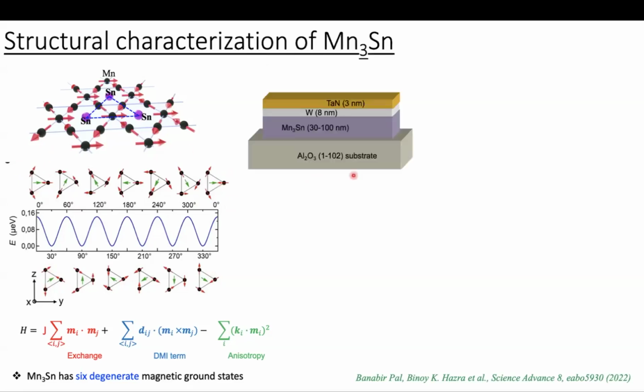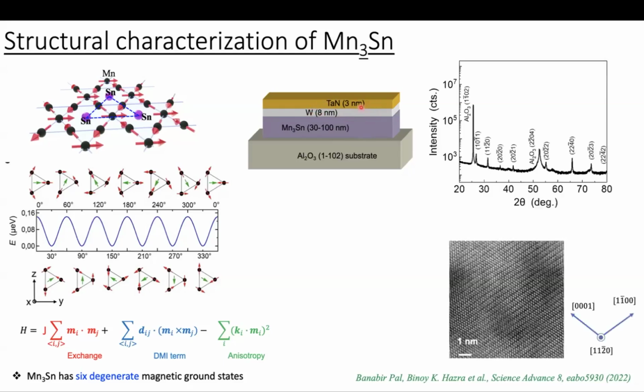So we have prepared manganese-3 tin samples with a thickness range of 30 to 100 nanometers on a sapphire substrate, where the Kagome plane was perpendicular to the film plane. And on top of that, we deposited an 8 nanometer tungsten layer, which acts as a spin current generating layer. The entire structure was capped with tantalum nitride to prevent oxidation.